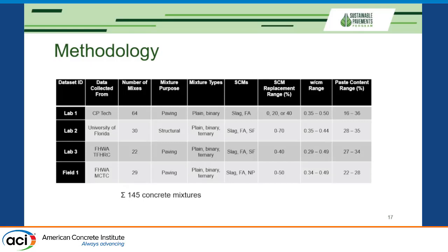So to do so, we have used 4 studies. One of them I have just showed you, that's field, and that's MCTC data with 29 paving mixes. We also had FHWA Turner Fairbank, different mix designs, and we have 2 other studies from CP Tech Center and University of Florida. Altogether, we have analyzed 145 concrete mixtures.